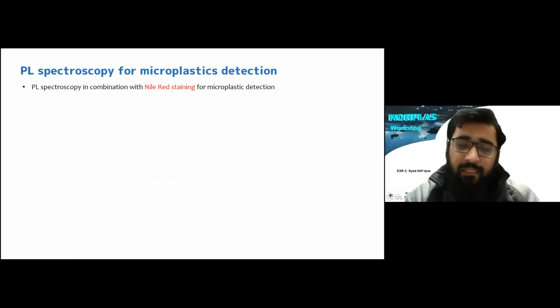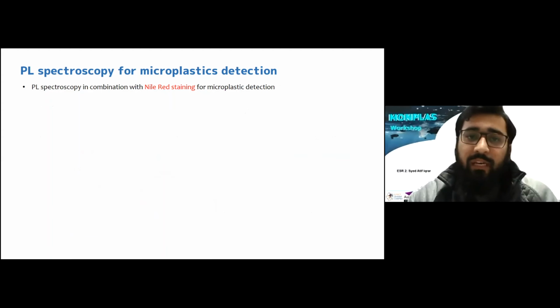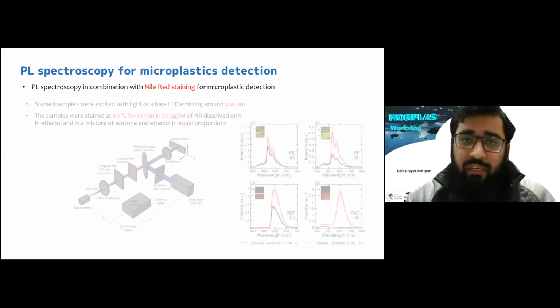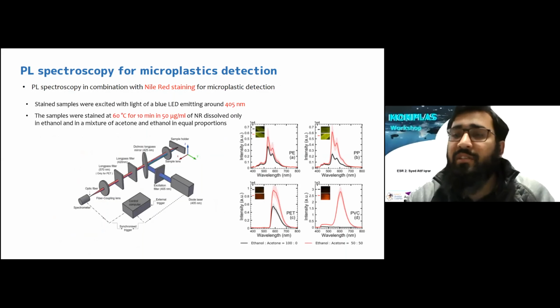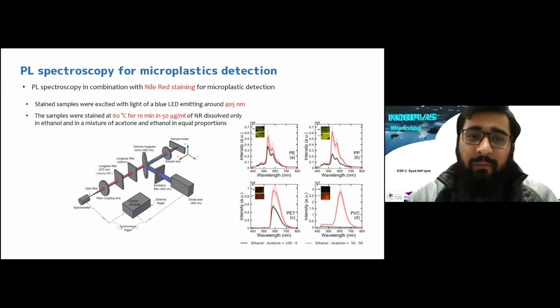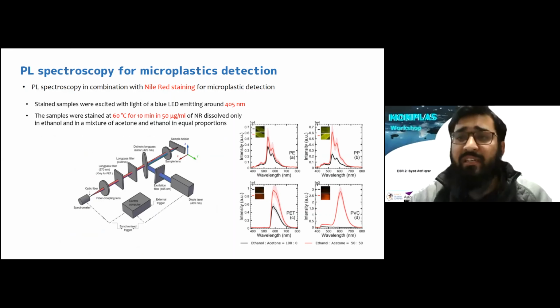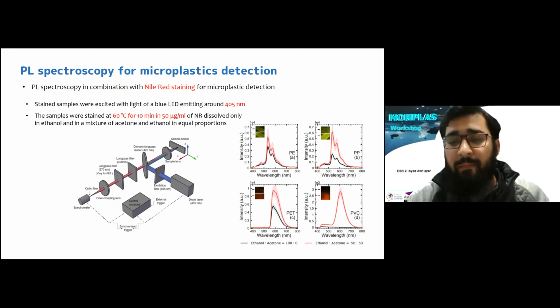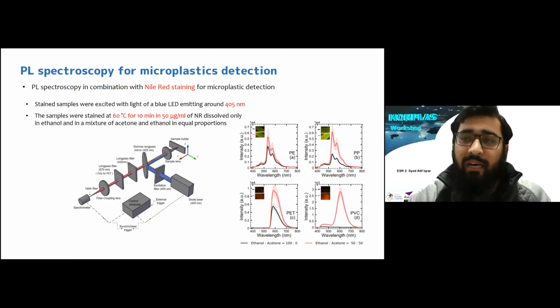This is another paper which is very important, and this time they used a staining protocol to increase the intensity of the signal. So this time they used Nile red as a stain, and they used the same conditions as previously with the 405 nanometer LED, and the samples were stained at 60 degrees for 10 minutes in 50 microgram per milliliter. They performed several studies, and the purpose of this study was to get an optimized or standard protocol for the Nile red staining.